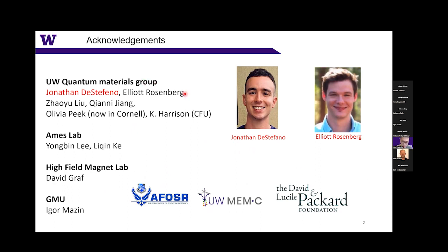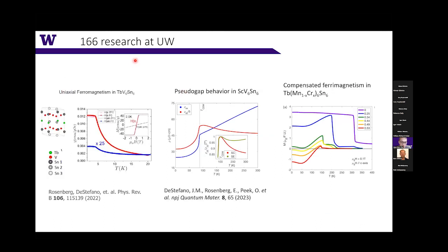Okay, so as I said, we have been venturing into the 166 compounds about maybe 2 years ago, and there are a couple of interesting results, a lot of which you have already heard in the previous talks. For example, the uniaxial ferromagnetism in terbium vanadium 6 tin 6, and we also see this pseudogap behavior associated with the charge density wave fluctuations above the actual transition temperature from the magnetotransport measurements in scandium vanadium 6 tin 6. But here I'm going to focus on this chromium substituted terbium manganese 6 tin 6. But I'll be happy to chat with you about the results of the other projects maybe after the talk.